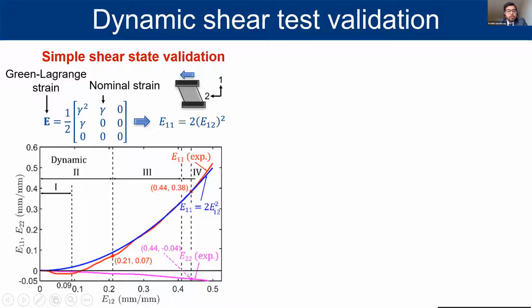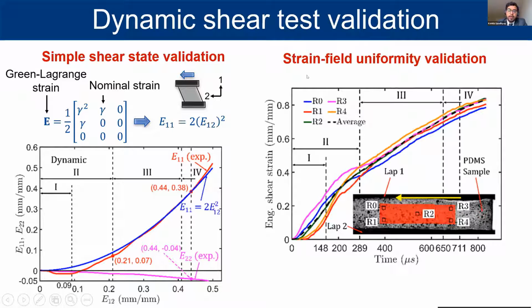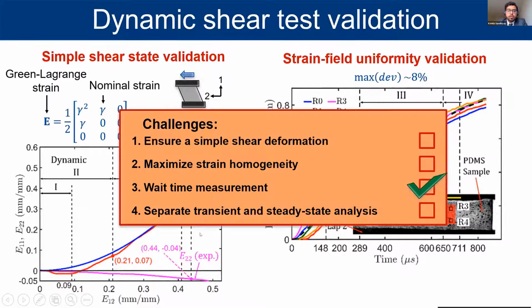Also, the E22 component, which should theoretically be 0, is at least an order of magnitude smaller than the other two strain components. This exercise gives us confidence that the deformation mode we are getting is correct. I also wanted to validate the strain field uniformity in the sample. And for that, I plotted strain in different small square shaped regions across the sample and compared that with the average. We found out that the maximum deviation in strain is around only 8%. So this exercise gives us confidence that we have the correct simple shear state of deformation with maximum strain homogeneity. And now we can separately analyze the two different stages of deformation.